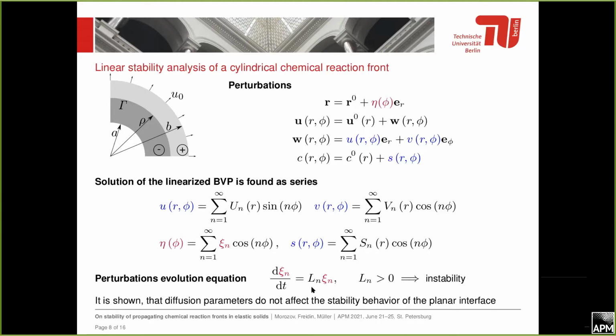And from this equation, you see the solution is an exponent. And basically, the sign of our Ln defines what it will be. So if the sign is negative, then the exponent with negative power will vanish in time, so we consider it a stable solution. If the power of the exponent is positive, then we say this is an unstable solution, physically unstable, and the lowest wave number n at which Ln is positive would be the failure mode.